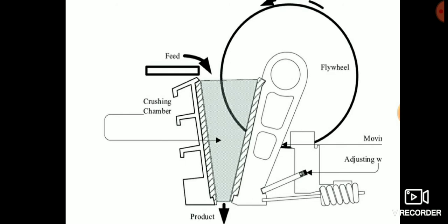Flake metal powders are produced by flattening equiaxed particles produced by another method. These may employ ball, hammer, or roll mills. When milling the original particles, lubricants are added to prevent them from welding and sticking to each other. Aluminum, copper, bronze, silver, gold, iron, and stainless steel flake powders are produced commercially by the milling method.